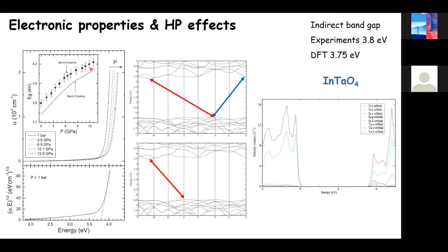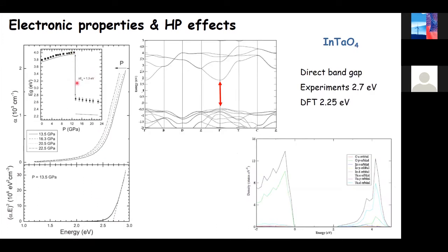And then when you have the phase transition, once again, we have the collapse. In this case, 1.3 eV, and the high pressure phase is direct band gap. And in the high pressure phase, we have a small red shift of the band gap with pressure. And everything is consistent with the results we got from DFT calculations.